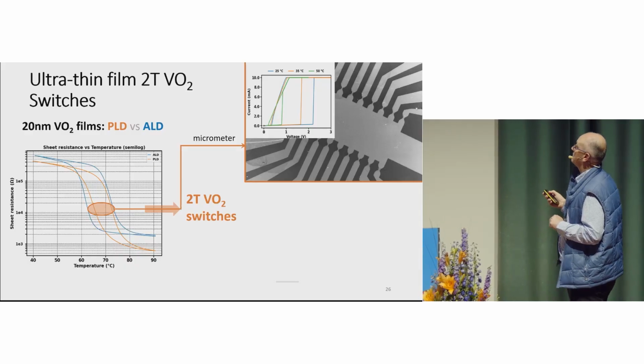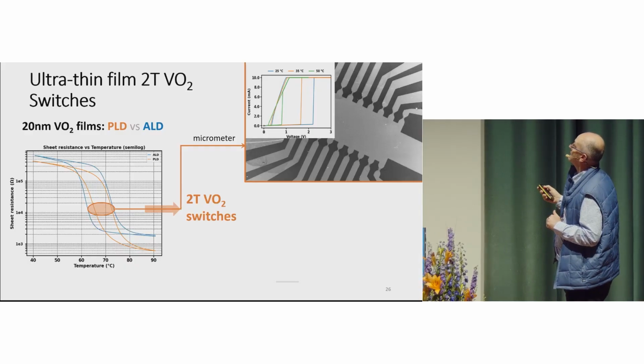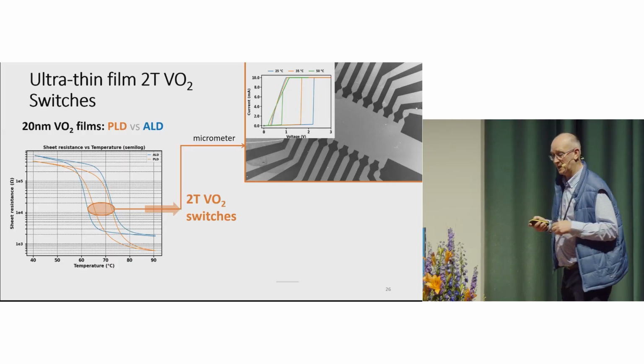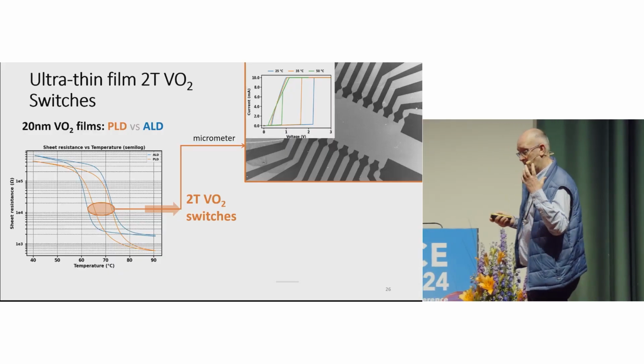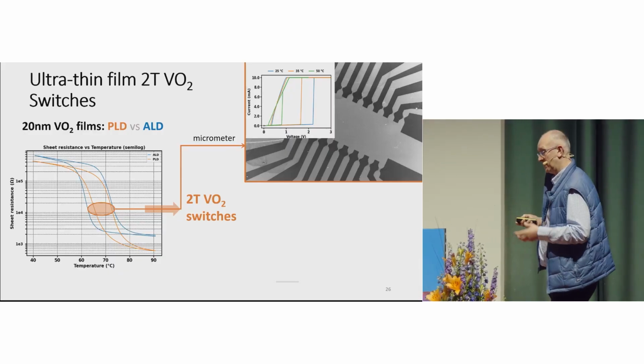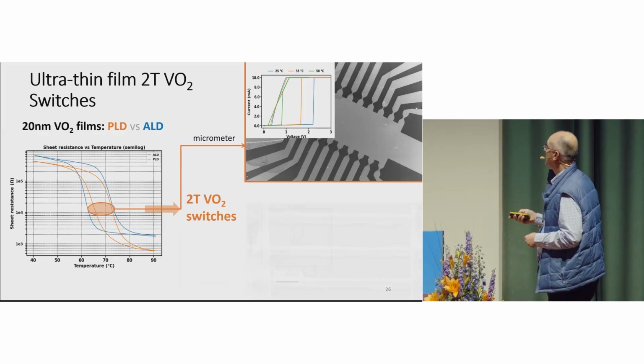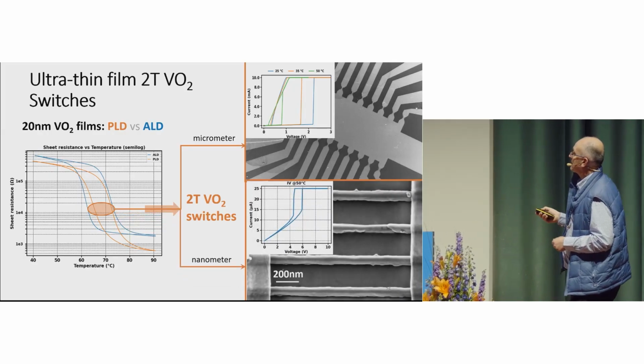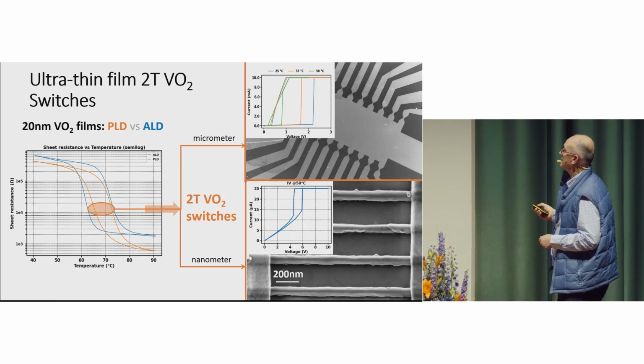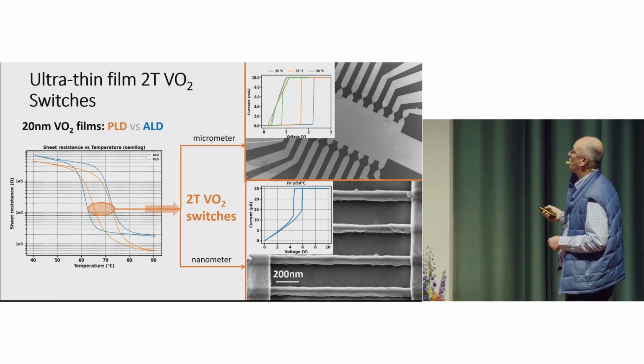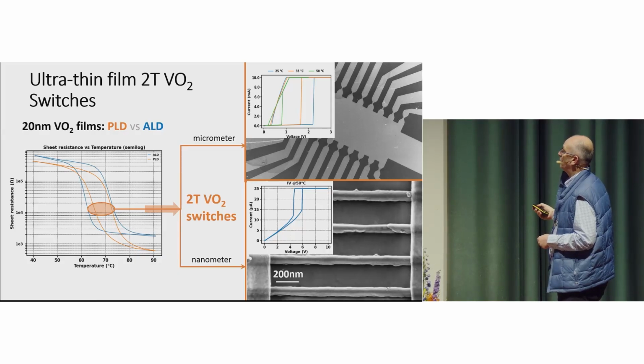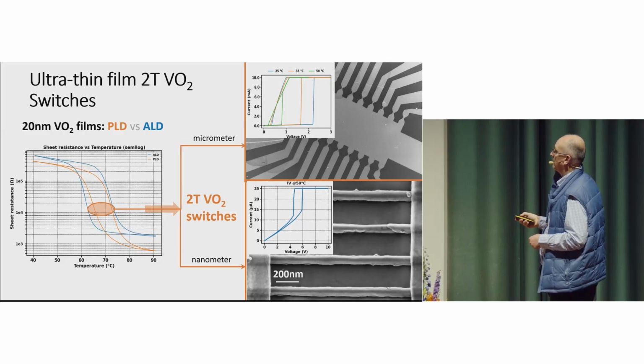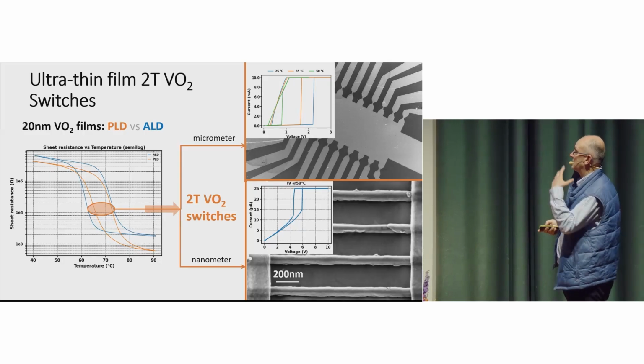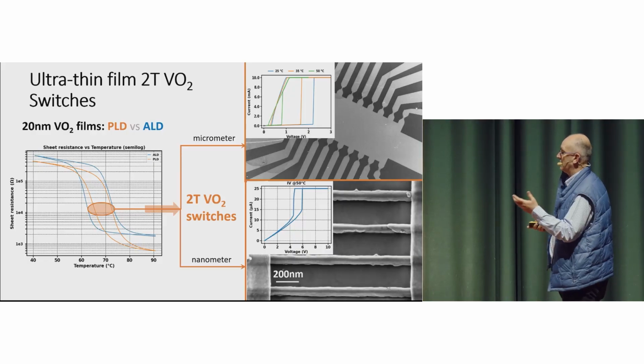Here we are building a sensor in which this switching hysteresis depends on the temperature, but these sensors are extremely sensitive to strain. So we can build a strain sensor that should be calibrated. It's combined stress and temperature sensing. Second thing, we have structured this at nanometer scale, and the property remains at nanometer scale, right? These are nanowire vanadium oxide. Of course, because of the form factor, they are more resistive, and we need a bit more voltage. But here, the phenomenon remains in this nanostructure. So this may be particularly designed for a strain sensor.